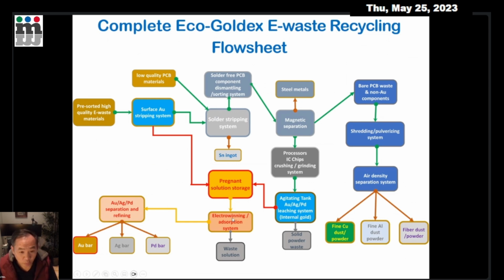We apply electrowinning to recover gold directly, or the gold and silver, if there is any silver together. The precious metal will come out together. They will be on the cathode. And this is the surface gold. And then after processing the surface gold, we'll process the solder tin, which acts as a glue to stick all the components on the PCB board.